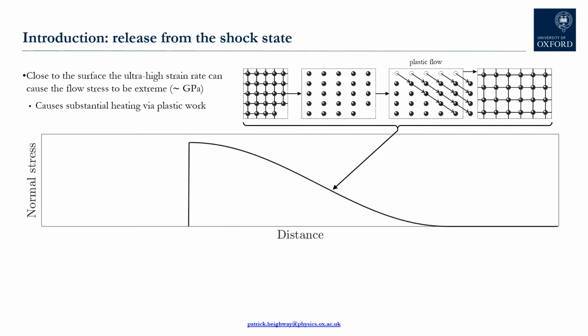Now, while that assumption might be reasonable for the kind of millimetre scale targets used in gas gun experiments, where the release rate is slow, we know that in the micron scale targets now routinely used on laser compression platforms, there's simply not a big enough runway, if you like, for the release wave to broaden over, meaning the release rate within these targets can be exceptionally high, and by that I mean in excess of 10^9 inverse seconds. Furthermore, it's now well understood that if you force a crystal to undergo plastic deformation that rapidly, you're going to have to exert shear stresses of order gigapascals to get it to do so. That is going to lead to a large amount of plastic work that will directly heat the crystal.